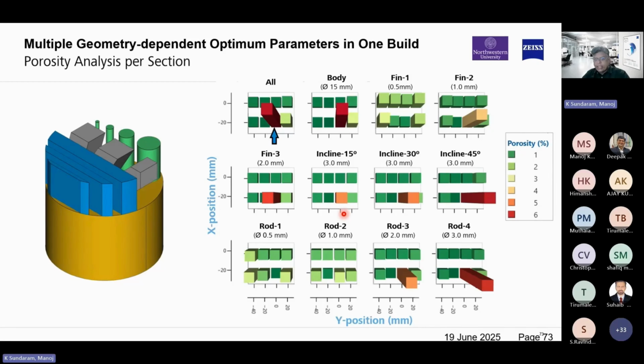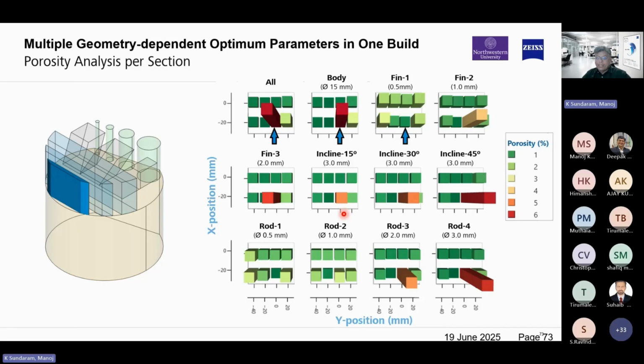In this case, we are looking at the XY position and the porosity content. There is also a relation to which feature has been printed, the body or a certain fin, a fin with a 0.5 millimeter wall or a fin with a 3 millimeter wall, as they can behave differently. And then different inclinations and different cylinders, how they have behaved with reference to the parameter set you have used. So this is a kind of advanced technique which we can offer.